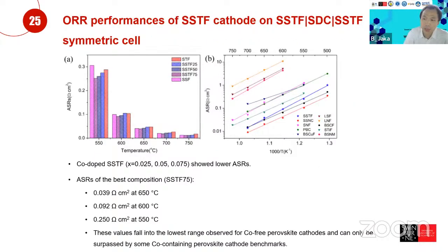And in here we then check the ASR at the different temperatures again, and for a different dopant component as well. Okay, so we find that the best compositions in here give us an ASR of 0.039 at 650 and 0.25 at 550 degrees Celsius. So this component is actually performing much better than the other two cathodes that I showed in the previous two different sets of slides.